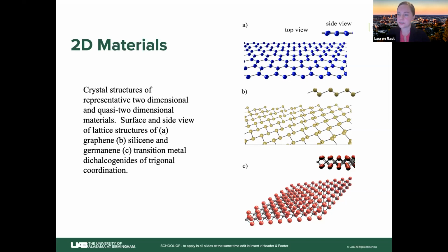Let's talk about some of these different materials. One of these materials that has a similar structure to graphene is hexagonal boron nitride, with a similar crystal structure to graphene. When hexagonal boron nitride is used as a substrate to suspend graphene on, the flat morphology and uniformity, along with the near match in the lattice structure of the two materials, leads to some advantageous electronic transport properties that are really close to a suspended sample of graphene.